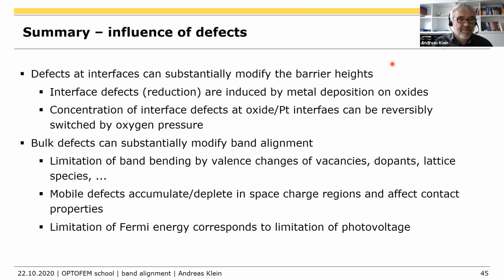Okay, that was about the defects. These are now extrinsic defects, not the induced gap states. They can substantially modify the barrier heights, in particular for the oxide materials. And there are various ways you can get defects at the interface, for example, by metal deposition, which you can easily get rid of by, for example, heating in oxygen. But also if you have bulk defects, they can be very important.